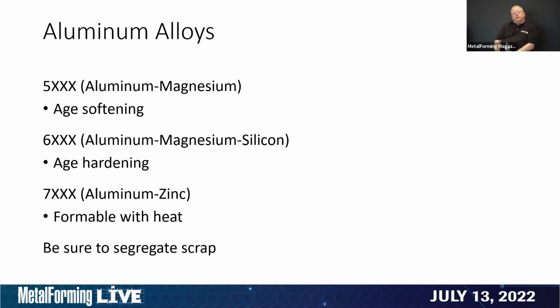But it's not just steels that are presenting us with challenges. Aluminum alloys also present their own unique challenges. Now, primarily for metal stamping, we're talking about, for the most part, the 5000 series of aluminum alloys and the 6000 series of aluminum alloys. We're now first starting to see the usage of 7000 series aluminum, but room temperature stamping doesn't really happen with great success. For that, we need what's known as warm forming or hot forming to make the best use of the 7000 series, which leads to the highest strength aluminum alloys.